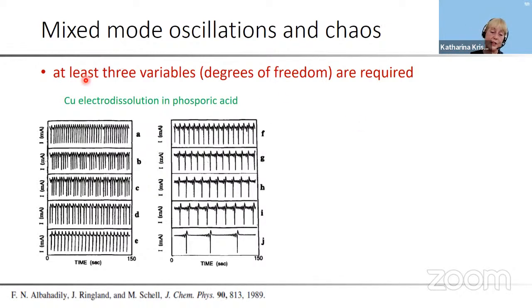And a beautiful example is shown here. This is a study by Schell and his group on the copper electrodissolution in phosphoric acid. And what you're seeing here is that at these parameter values, you have mainly oscillations with a large amplitude. Once in a while, there's an oscillation with a small amplitude, so it is interrupted. And as a parameter is changed, the small amplitude oscillations interrupt the series of large amplitude oscillations more and more often. Here, every second large amplitude oscillation, there's a small amplitude oscillation.